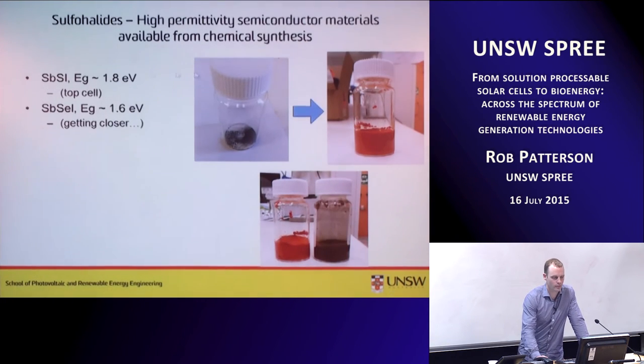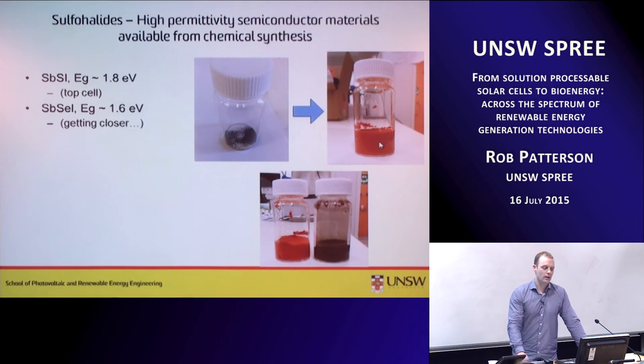So just out of interest's sake, here's the raw materials and here's what happens after you do the synthesis. So you can see that there's a dramatic change. We end up with a gel of nanowires, and you can make antimony sulfoiodide or the selenoiodide. And the selenoiodide has a slightly lower band gap, and so it's a little bit closer to what the optimal one is for solar energy conversion. And the other thing that I want to mention on the slide is just that this process can happen in air. So this is an air-stable material.